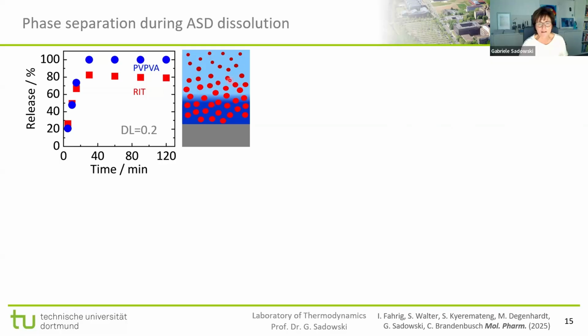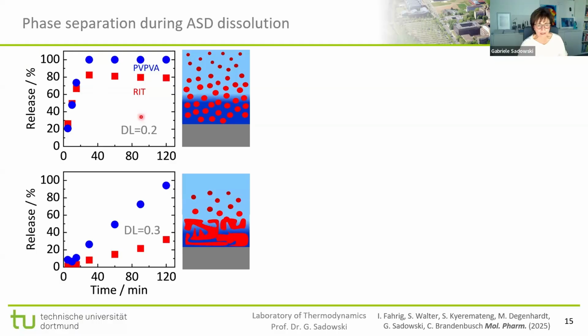We still have droplets also after dissolution, but this is fine because they do not crystallize, and that's why we don't call this dissolution but release, meaning that we have now Ritonavir-rich phase droplets in the aqueous body fluid, and they will then release the API Ritonavir. So this is something which is okay, and this is the release behavior that we observe for that case.